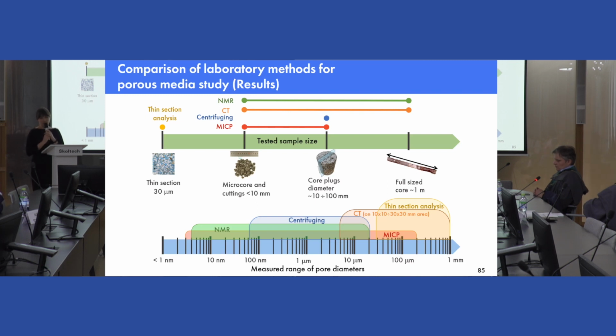Also, NMR is not a direct method for studying porous networks. It still measures the relaxation of protons. It does not give us a direct answer on what pore size we have, and thus we need to calibrate it to other tests. So in my study, I apply not only NMR but also computer tomography and centrifuging. But these methods also have their limitations in terms of resolution first, and in terms of the detail of the steps applied. And considering CT, it has really advantages.